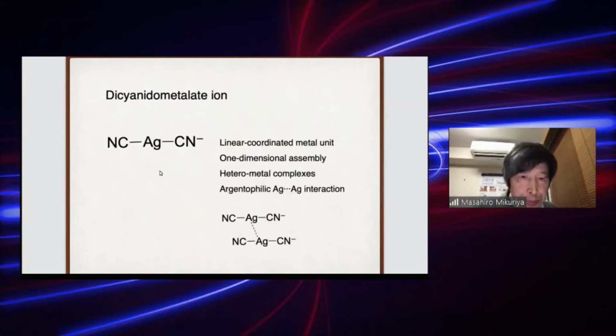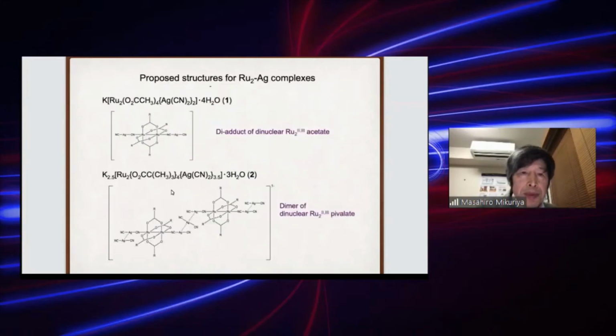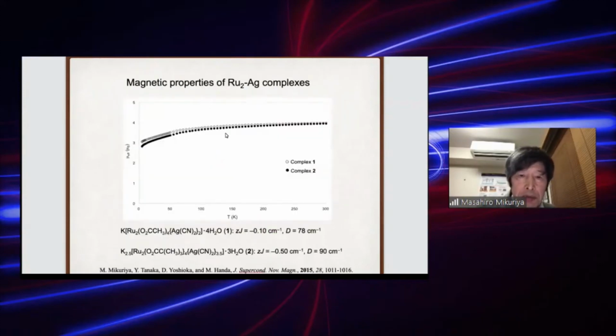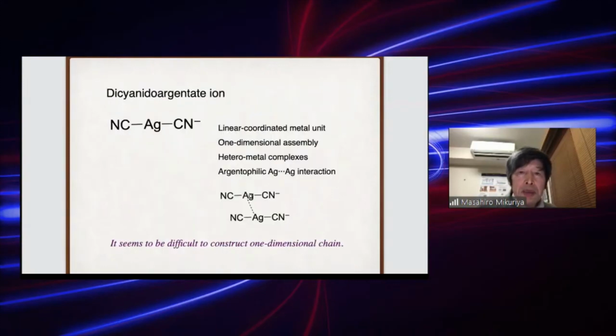So we moved to use inorganic cyano groups as linker groups. So dicyanoargentate, we obtained some adduct, but we could not get chain compound for these systems. Magnetic property is like this, with very weak anti-ferromagnetic interactions. And we could not obtain a single crystal for this system.